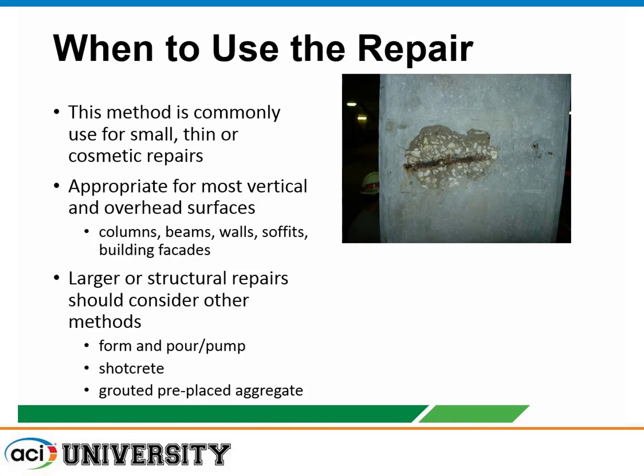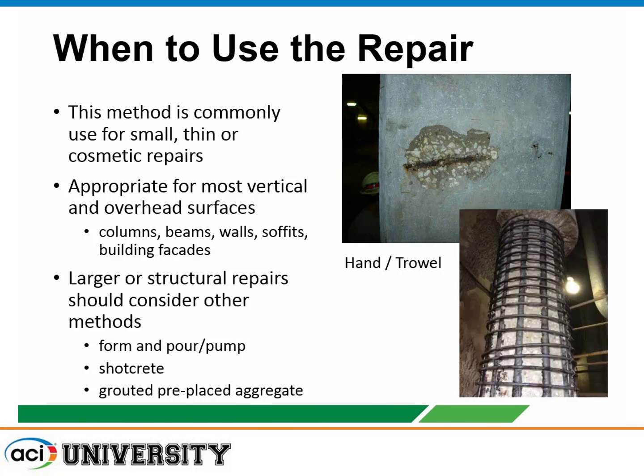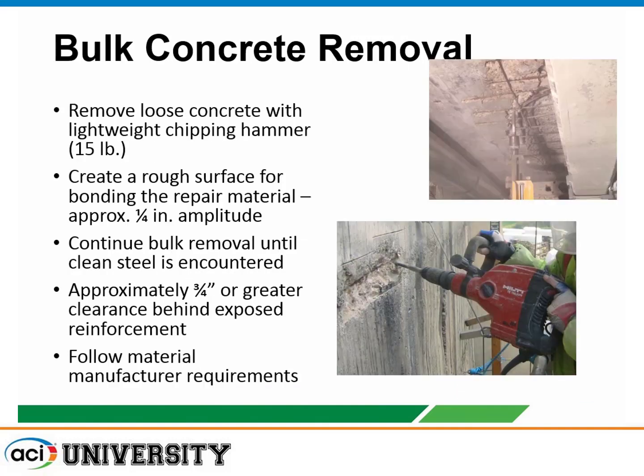Once again, we're looking at smaller repair cavities for hand or trowel-applied repairs, as opposed to major structural repairs of a column where you'd use a different method. The process really starts, after understanding the cause of the problem, with bulk concrete removal. We've seen the need to use lighter weight chipping hammers — heavy hammers are hard to use physically and can also create a lot of concrete damage, especially when dealing with small repairs and working in detail around the reinforcing steel.